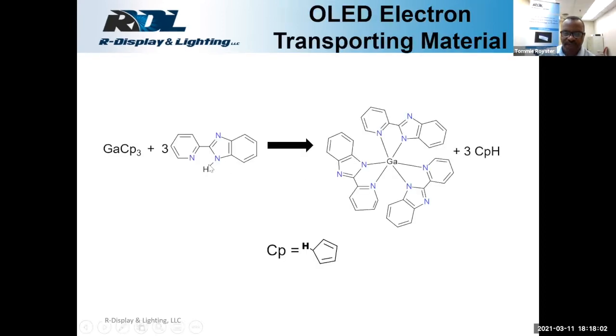While I was at Eastman Kodak, one of the projects I worked on was the development of electronic materials, specifically electron transporting materials for OLED. Here, we're showing that we can use the lability of the Cp ring in solution to react gallium cyclopentadiene with pyridyl benzimidazole to form this following gallium chelate. This material, based on its high LUMO electronic structure, provides a very efficient electron transporting material for OLED applications.